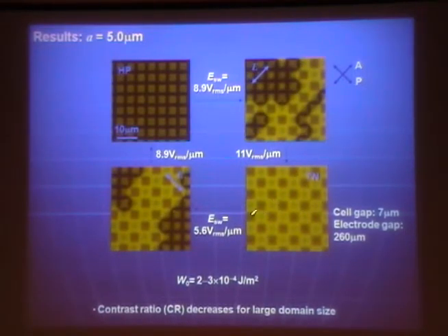Different contrast comes from a little bit of misalignment of polarizer and analyzer. And this is an intermediate state. So you can just go in a complete cyclic manner from a dark state to a bright state, passing through this intermediate situation. Like I said, those dark domains are boundaries between two different topological connections of the domains, and they are connected with the macroscopic disclination lines.